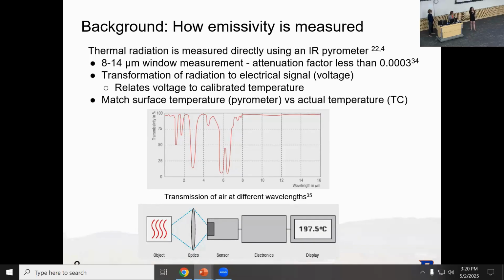The benefit of an IR pyrometer is that pyrometers measure infrared radiation at just 8 to 14 microns in the spectrum. This is important because that is where atmospheric effects are very minimal. In this graph, we can see at 8 to 14, or 8 to 16 in this case, the transmission of air is really high, so we're not going to have the effects of the Earth's atmosphere influence our measurements.